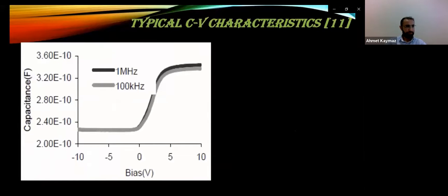The typical behavior of CV characteristics of MOS devices is shown in the figure. In this figure, three regions which are well known in the literature are seen, namely inversion, depletion, and accumulation regions. However, these can be divided into 5 regions, which are strong accumulation, weak accumulation, depletion, weak inversion, and strong inversion. In the ideal case, the value of capacitance is almost independent of voltage in the strong accumulation region, whereas it becomes a weak function of frequency in the weak accumulation and inversion regions.